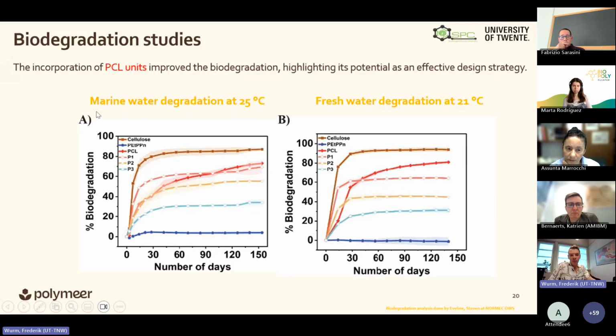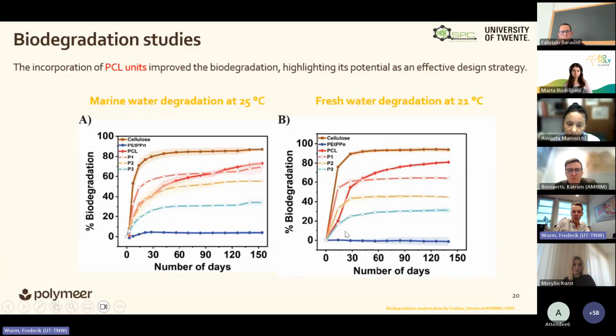So we have here just two examples, marine degradation and freshwater degradation. And you see the brown curve here, cellulose, as our control sample. And we see in biodegradation, the polyphosphonate here is not biodegrading, but it's hydrolyzing very fast. And because of this hydrolysis, when you look at the red curve in both cases, especially in the freshwater, the red curve is the caprolactone alone. It also biodegrades, but as soon as we have the copolymer structures, the breaking points of the phosphonates accelerate the initial biodegradation rate. This happens in freshwater, but it also happens in marine water.